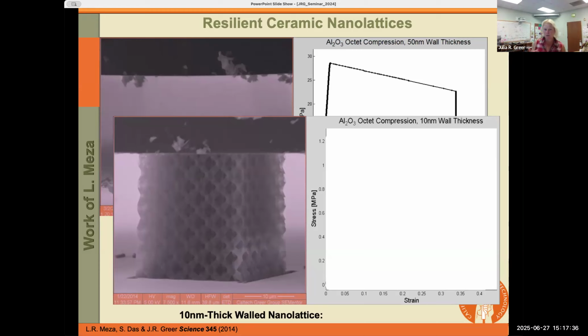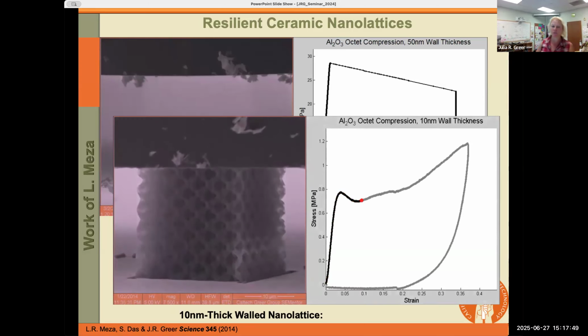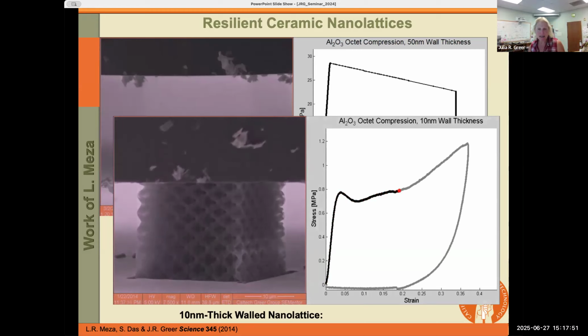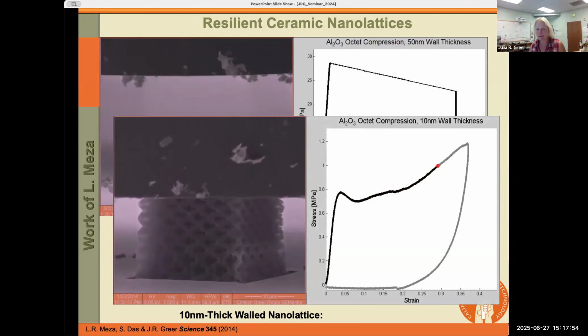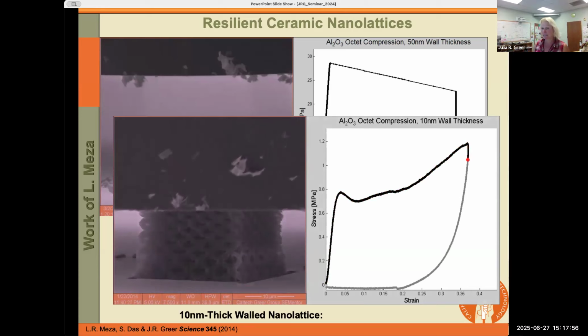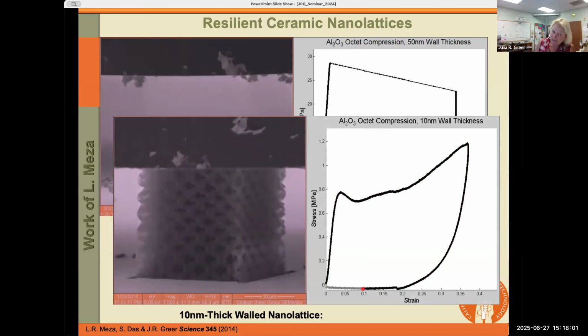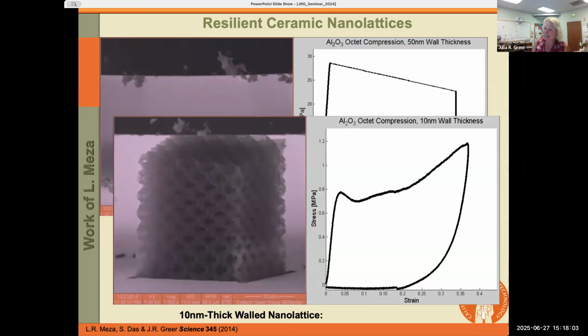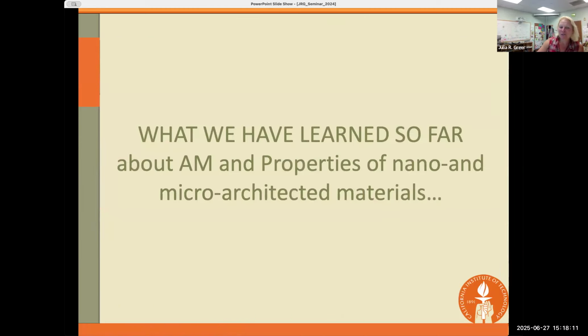If you were to just project based on what we saw in the previous experiment, it should crush and die even more readily, because now the walls are even thinner, and it's even more probable that this very brittle nanolattice is going to fail. So let's see what happens. What we're observing here is that this very brittle, very ceramic nanolattice is being compressed to almost 50% and then fully recovers. So if that doesn't convince you that there is in fact a size effect, there's no point in continuing with this seminar.